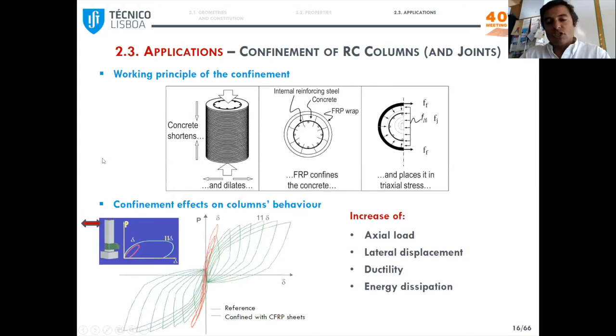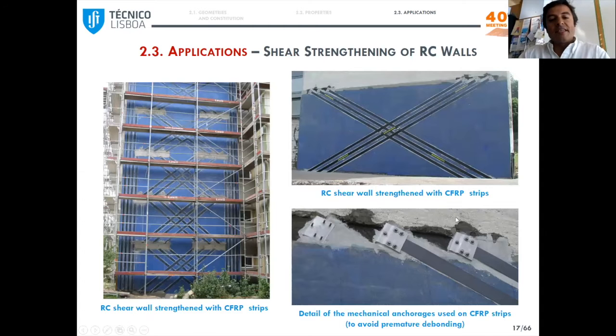So when we go to the structural scale, for instance, vertical member under lateral loads, this will result in a significant increase of axial load, but also of lateral displacement, ductility, and energy dissipation. Here you can see another application, in this case of CFRP strips, installed in a cross shape for the shear and seismic strengthening of concrete walls. So the strips, in this case, are bonded with epoxy to the substrate, and they also have these mechanical anchorages to prevent premature debonding, which is a typical failure mode in these systems.